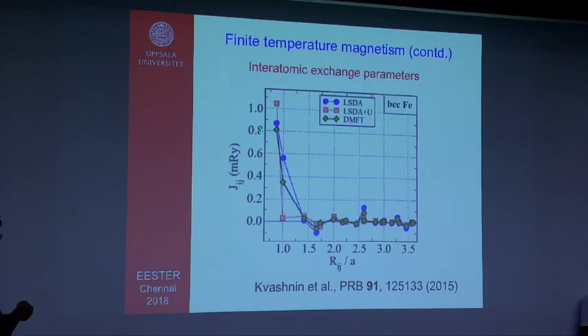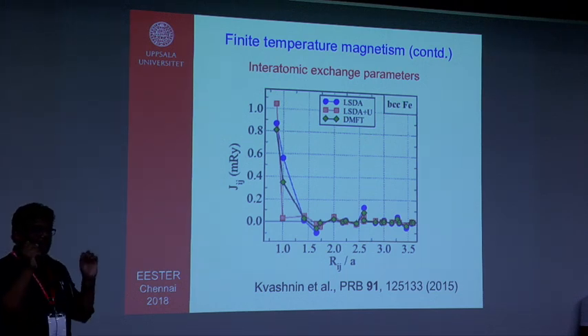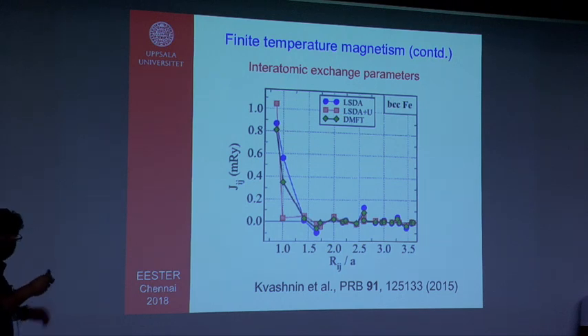We see that the first level interaction is very high, and then it goes down like this. Now, for a metallic ferromagnet like BCC iron, we know that the RKKY interaction plays an important role. This is a very long-range interaction. That's why these calculations have to be done very carefully to find out for long distances whether these are really ferromagnetic or antiferromagnetic.